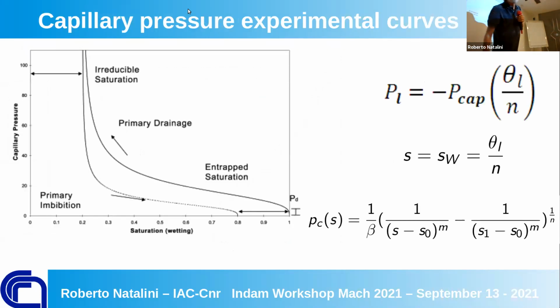On the other hand, the shape of capillary pressure comes just from experimental curves. There is no theory of that. There are some people trying to understand that for a single material, but it's very difficult. And also from the distribution of pores, it's difficult to derive the real shape of this curve. And so the capillary pressure is usually infinite at this threshold, the same threshold for the starting of the capillary rising. And usually you have different curves for absorption and drainage, when you are emptying your pores. So you have some hysteresis here, but for now you only have to see the capillary rising. For instance, this kind of formula can be used, just a phenomenological one. So you have some parameters to be fitted.